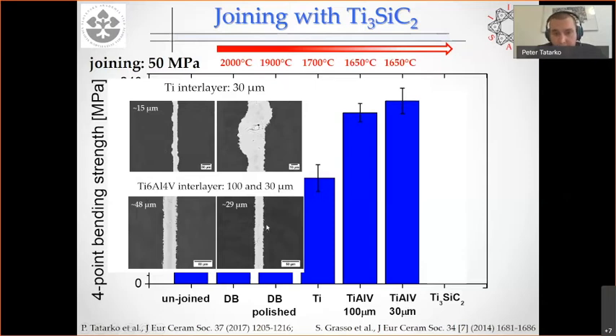And the second important issue, which I would like to point out, you can notice here that the alloy was very reactive. You can see all this nail-like structure. So it can damage either carbon fibers in the composite or the protective silicon carbide layer. So that's why we needed something else.